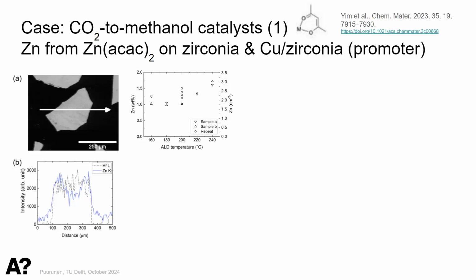So we have been embedding our ALD treated zirconia particles in a resin, cutting them and taking a cross section. And this is how our zinc content looks. So we have zinc. Actually, it looks like it makes a little dip in the center. Anyway, we have zinc everywhere and we have gone to testing with these. We have tried this new zinc precursor, acetylacetonate, because we were not able to use the pyrophoric diethyl zinc that everyone else uses. And we have shown that you can also add zinc from this reactant, and it's not very temperature sensitive. Once you are below 200, you get about the same zinc amount irrespective of temperature, but if you go higher, then you probably start decomposing.